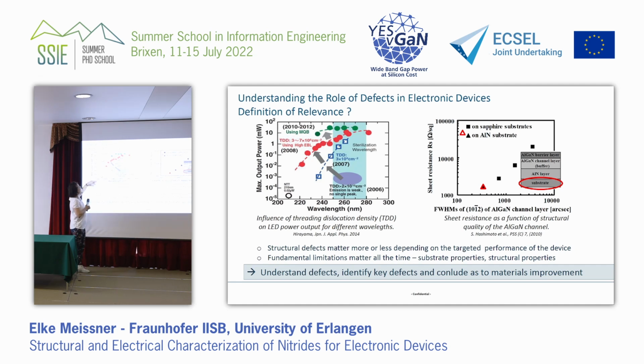If I look here, for example, this is an optical device, but it doesn't matter, it can be any other. You see depicted the influence of the threading dislocations in the device on the output power of an LED at different wavelengths. We have something like 10 to the 10 dislocations in the epitaxial layer, and we find some power output of this LED at 260 nanometer wavelength. It's fine. But we see that we have no power if we go to shorter wavelengths. If our target is to operate a device at shorter wavelengths, the total number of dislocations matters a lot.